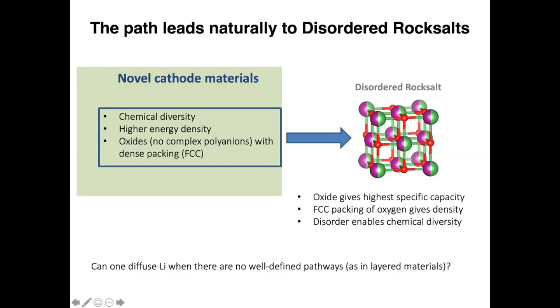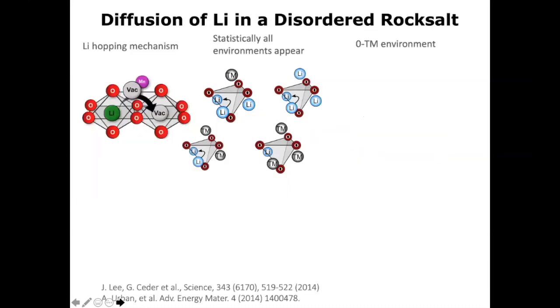So we have all worked extensively on layered materials where there are very well-defined two-dimensional pathways for lithium, spinels where there are three-dimensional tunnels, and lithium iron phosphate where there are one-dimensional tunnels. So the question is, how do you diffuse when you have a cation-disordered system where there are no specific sites for either the lithium or the transition metal cations?